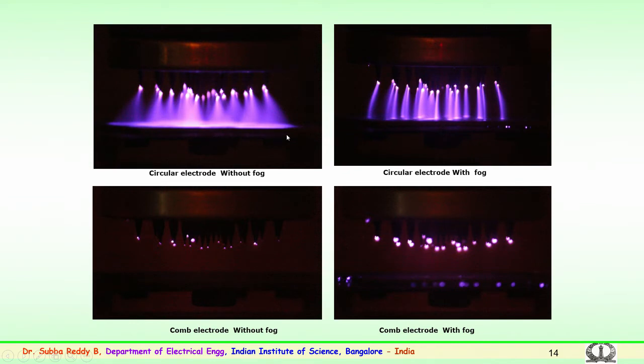It continuously impinges on the sample, and depending upon the number of hours the experimentation proceeds, the surface degrades over a period of time. This is for the dry conditions, that is without any application of mist or fog. Here you can see for the similar electrode, when fog is applied into the chamber, either acidic or normal fog, the discharges completely change. Instead of complete spread, you can see a very narrow type of discharges with higher magnitudes impinging on the sample. This is much more rigorous and of much higher magnitude in comparison to the normal conditions.